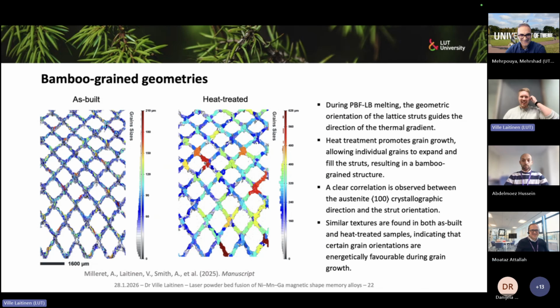It's okay. So as built, we can see that there are very tiny grains, but then in the post-processing heat treatment, we expand those grains and they fill these narrow struts, and we can get a structure with interconnected struts of single crystals, and then node areas where we have several grains. In an external magnetic field, this type of structure can strain 6% in the martensite. So it is effectively a good actuator approach, but of course it takes a lot of tailoring into what should be the ideal strut angle and the ideal way to implement the actuator based on this kind of structure.